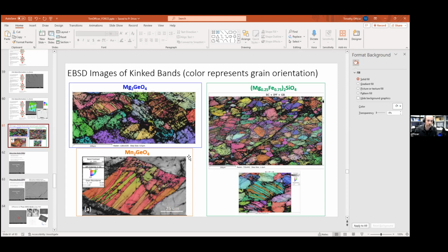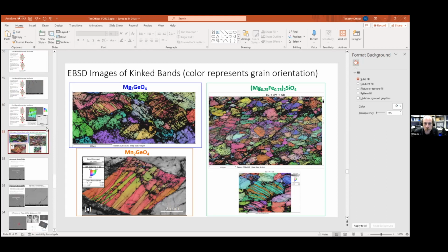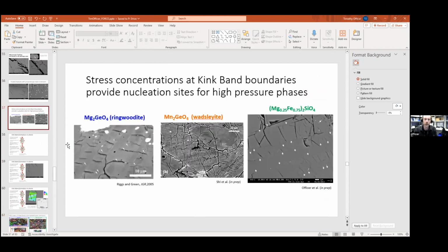She says, okay, I don't see that either, but kink bands are nice places for spinel to nucleate. They are. I think I have an image of that too. So here, this is Mg2GeO4, Mn2, and then the olivine. And you can see that at these bands, there's a lighter phase. You have a lot of stress buildup at the interfaces of these bands, which provide nucleation sites for the ringwoodite or wadsleyite.